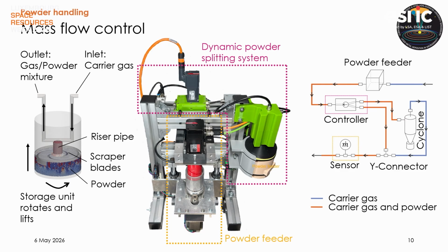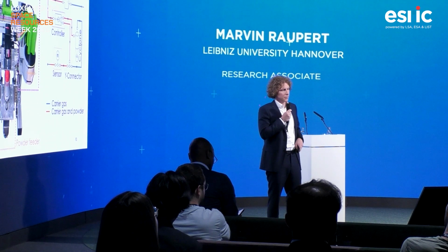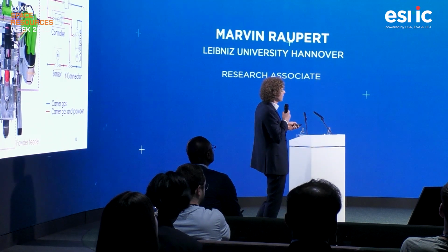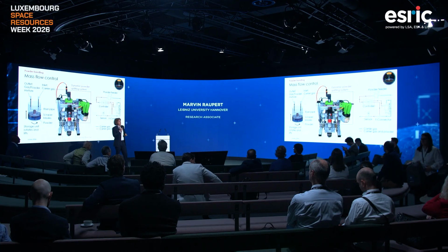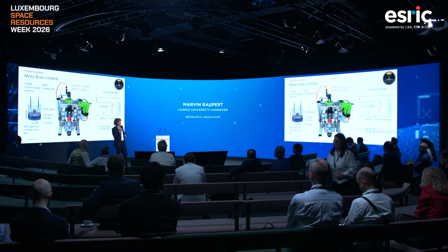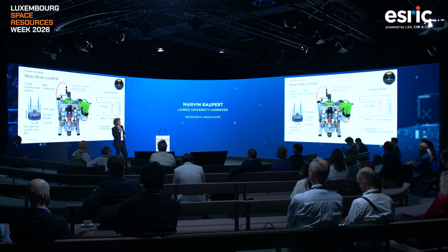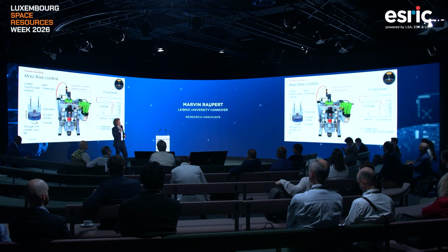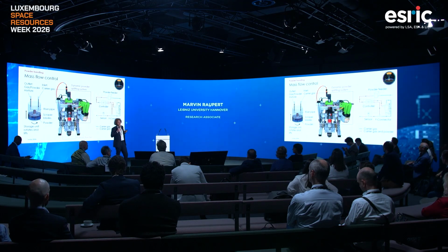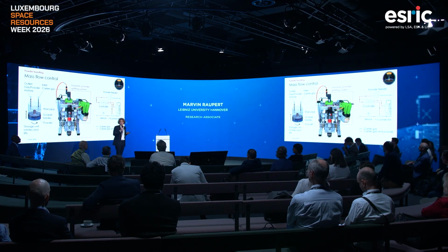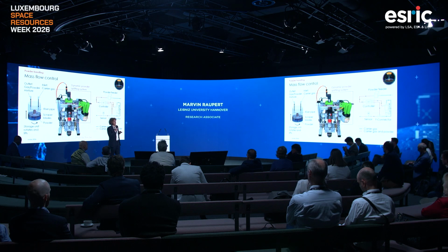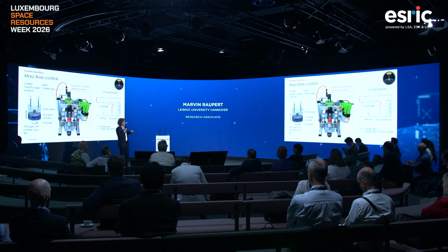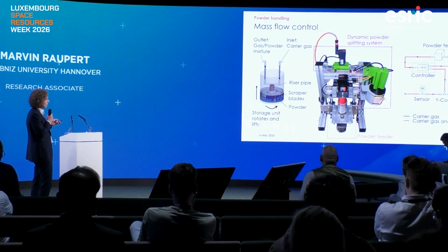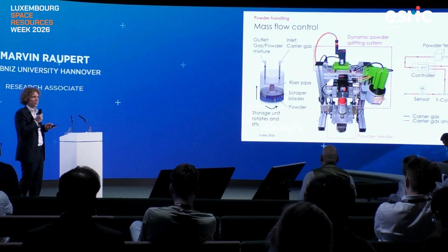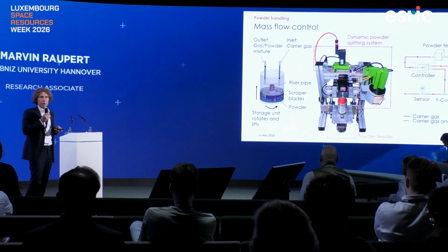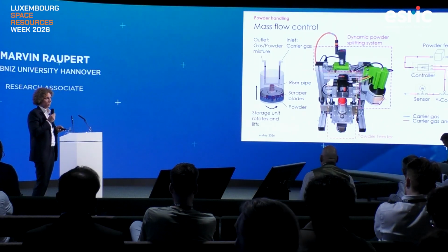So in fact of that, we added a dynamic powder splitting system. The function you can see on the right side. After the powder feeder, so imagine we have now a powder mass flow of 5 grams per minute, but the deviation is really high. And what we are doing now is that we are reducing the mass flow to, for example, 4 grams per minute, but now we could keep it more constant. So there's a controller unit, which is a splitter system, 1 inlet, 2 outlets, and the angle of the splitter could decide which amount of powder is in channel A or channel B, for example.